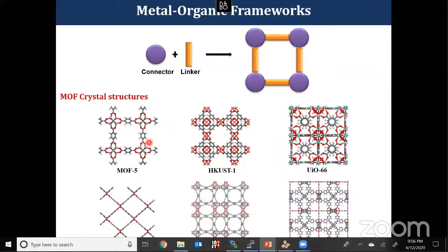But as a computational chemist, I can just select the molecule and do the modification using appropriate software. I will do optimization. Then I will get the crystal parameter ABC values. Then I will go for further study. If I want to do electronic structure or band structure calculation, I can do. If I want to do gas storage, I can do. So I can compare the results of both pristine as well as substituted MOF performance at various temperatures and different pressure levels. So I can quantify whether a MOF is really going to work for a particular study before it is synthesized. For me, it will take less than a week to generate the whole data. So from that point of view, it is very easy.